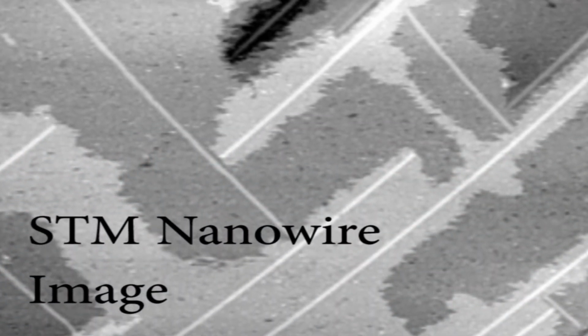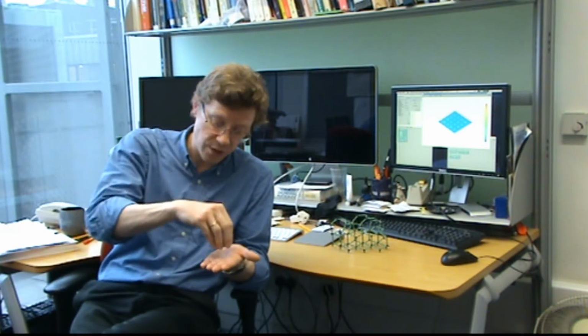So it's the nanowires, they're very beautiful. If you put down tiny gold dots, maybe a few tens of nanometers across, remember a nanometer is a millionth of a millimeter, and then you introduce, say, silicon vapor or germanium vapor, these nanowires will just grow spontaneously. And you can control the growth, so you can control the radius, the size of them. You can also coat them in a different semiconductor, which gives them very, very interesting properties.